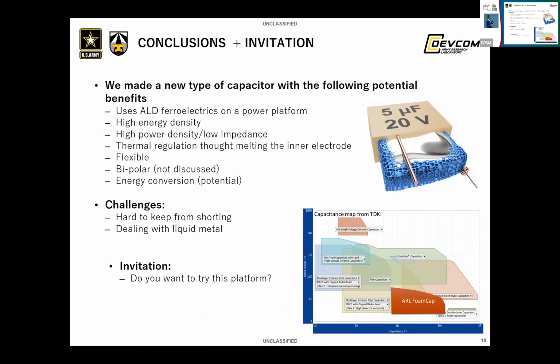So in conclusion, we made a new geometry of capacitor that takes advantage of ALD ferroelectrics. It has high energy density. It could have high power density because we showed low impedance. You could think of doing thermal regulation by melting the inner electrode or even flowing the inner electrode in a closed loop. I didn't show it here, but they are flexible. This is something that John keyed me in on, is that the thin films are much more flexible than you would expect. The capacitance density here kind of sits between MLCCs and electrolytic capacitors, but these are ALD ferroelectric, so they are bipolar, which could be really helpful in some certain situations.